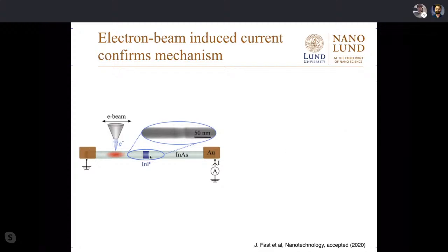So you take a nanowire with a barrier, put contacts on them so you can draw a current. And then instead of light, in this case, we use the electron beam of an electron microscope. So this is basically a brute force experiment. You blast electrons with kilovolt voltages, so huge compared to light, 1,000 times more than photons, which also create electron hole pairs in some cascade of processes. So it's not pretty, but the advantage is you can do it highly localized, and you know exactly where on the nanowire you are.